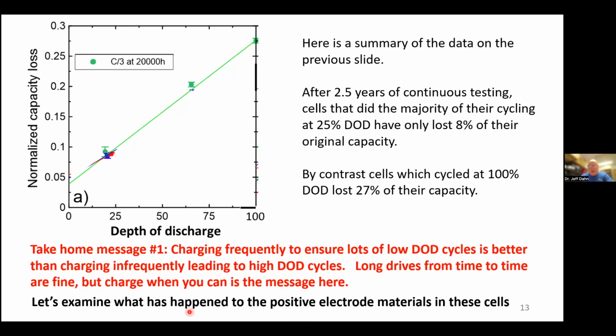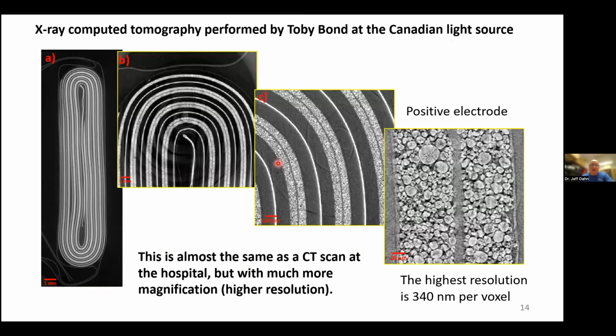It's really interesting to see what's happened to the positive electrode materials in these cells after this 20,000 hours, or 2.5 years, of testing. It turns out that you can do X-ray computed tomography, almost like a CT scan at the hospital to look inside your body for problems. We can do the same thing to look inside lithium-ion batteries, but with much higher magnification. This is an X-ray CT of one of the cells that was being tested.